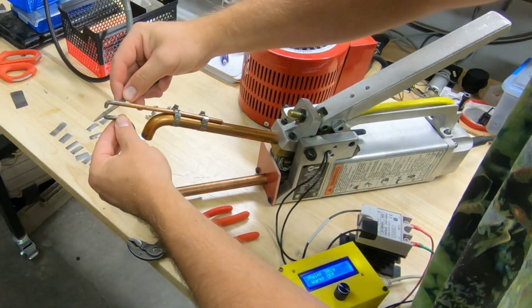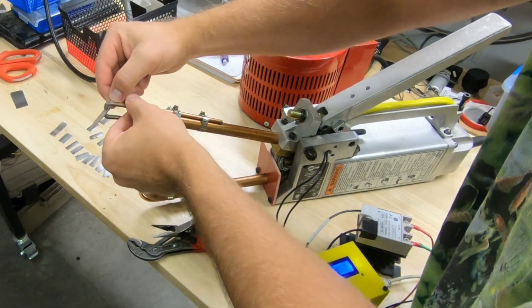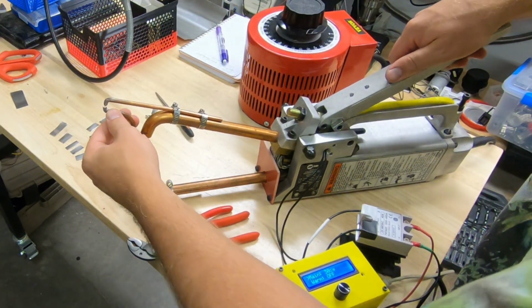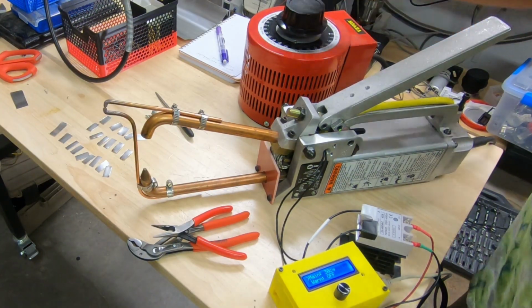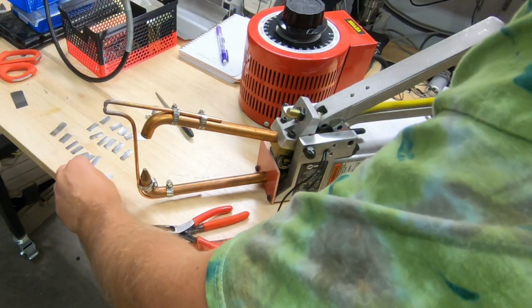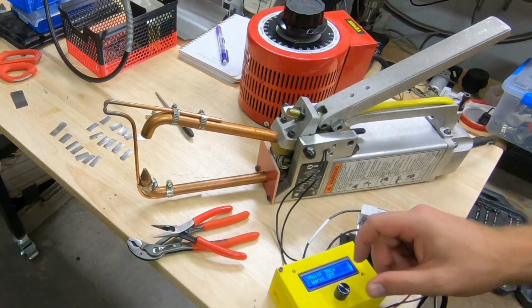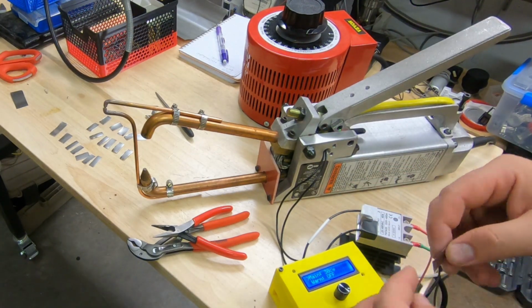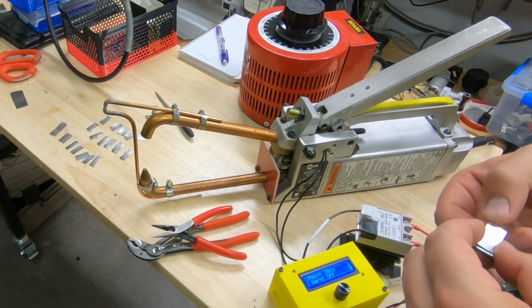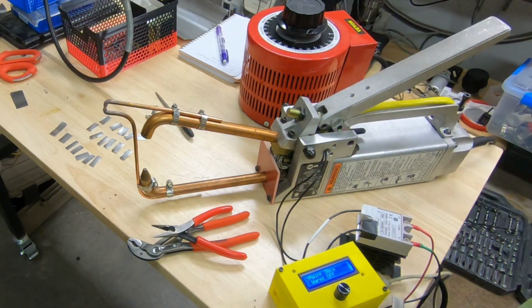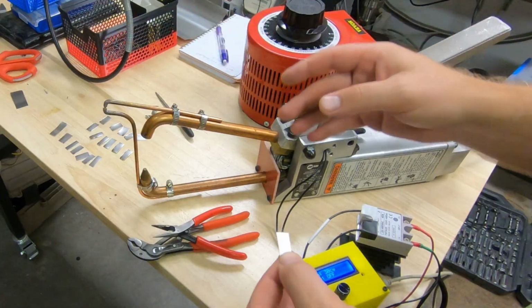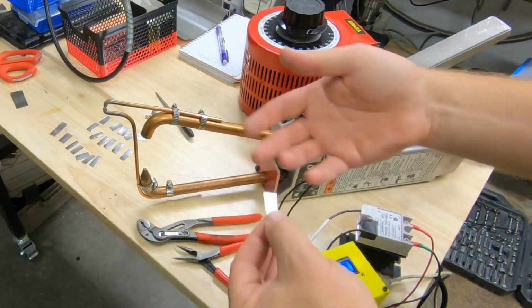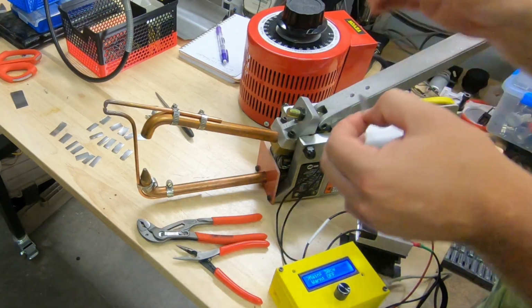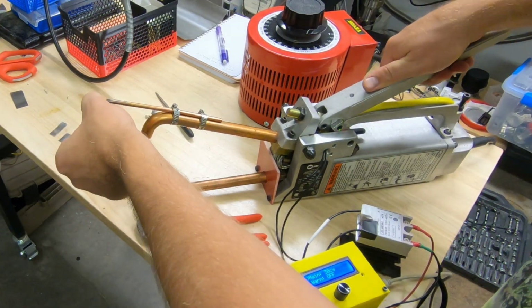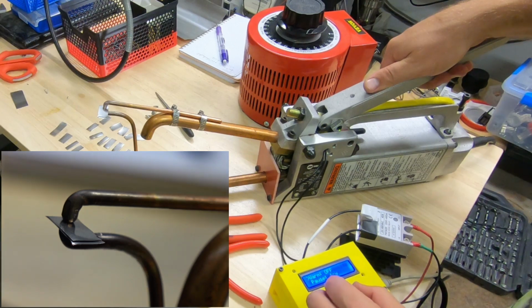I'm just cleaning this up a little bit, because that melt gets on there and then it'll mess with the contact. So 70 volts seemed like it was still too high, and I'm going to use the pulse control as well to see how good a repeatability we can get, and if we can really nail down a good spot where you get good fusion but it doesn't melt to the electrode, sort of a sweet spot for welding this material. So we're at 70 volts and I've got 30 cycles selected, which translates to a half second pulse time.